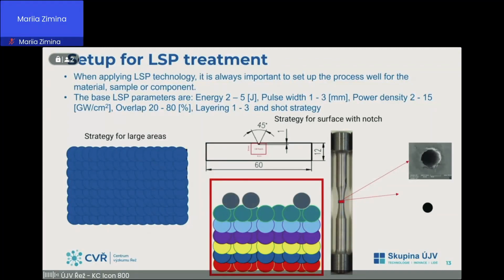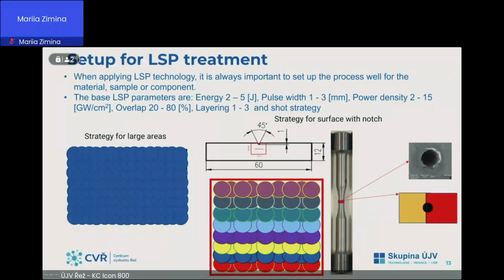The basic LSP parameters are energy, pulse width, power density, overlap, layering, and shot strategy. On the slide you can see some strategy. The first strategy is for large area. It's simple, it's good for increasing the hardness of the surface. And for a surface with notch, we used a special strategy with a lot of pulses. You can see in the center.